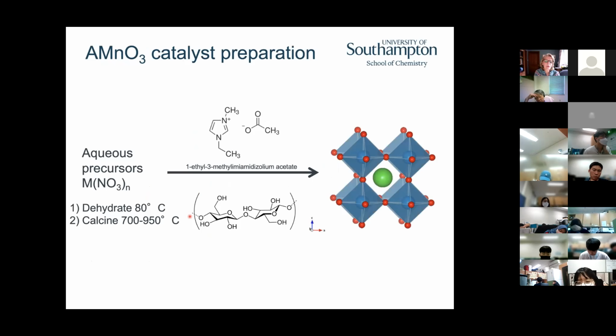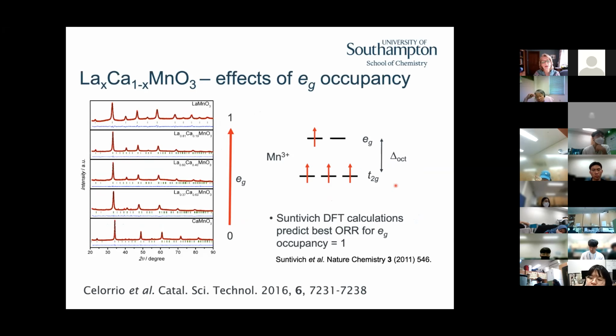So we came up with this method in collaboration with the people at Bristol. What it uses are the aqueous nitrate precursors, but then we use this ionic liquid as the solvent, and then we add cellulose, right? And that allows us to make the perovskite structure with very small particle sizes, so we have a large surface area. This is the work of Veronica Kilaria from my group and that of David Fermin's group in Bristol.